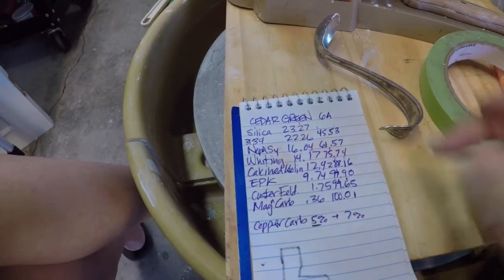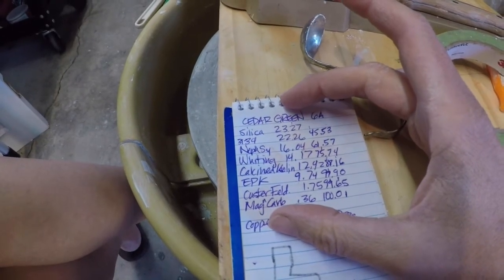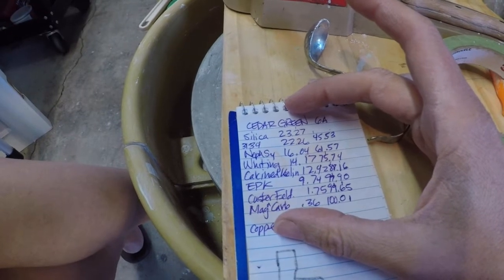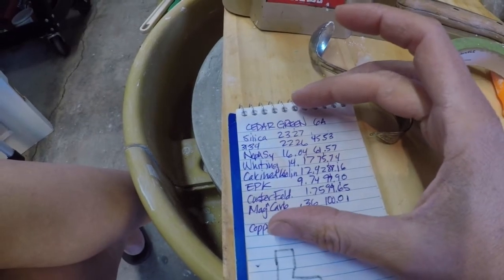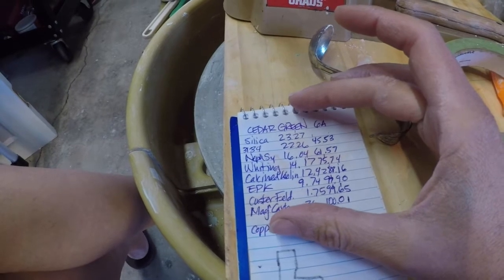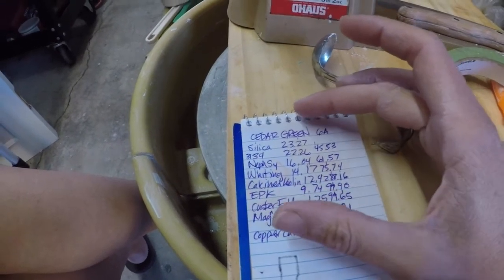But for me, I'm going to see if this works on my clay. There are different glaze effects, or defects, that might happen with this base glaze. If it doesn't work, there are some things I can do. If it starts to crackle, I can add some boron to this recipe, and our best boron is going to be Gerstley Borate.